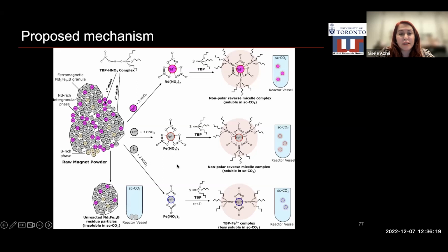Since iron occurs in 2 valences, the extraction of iron would be lower than the extraction of the rare earths that occur only in 3 that have higher aliphatic chains. Later on, we prove this structure with DFT modeling and XAS characterization.